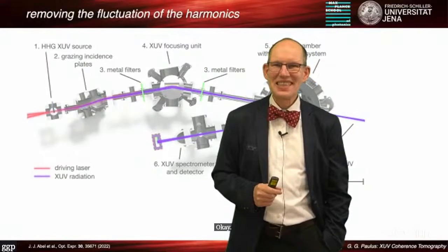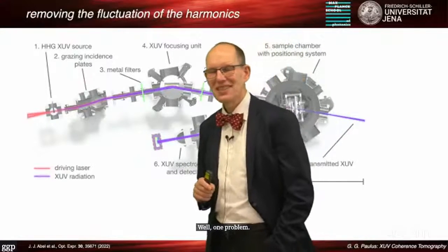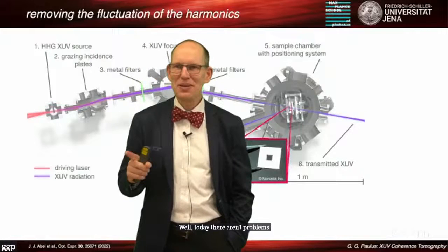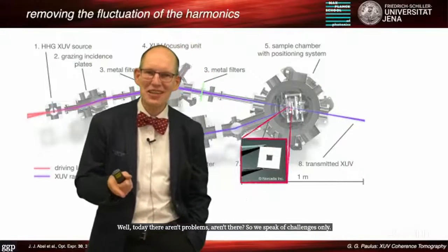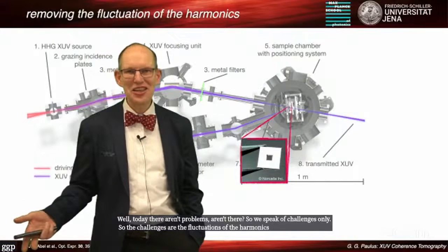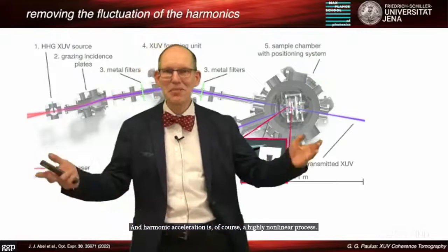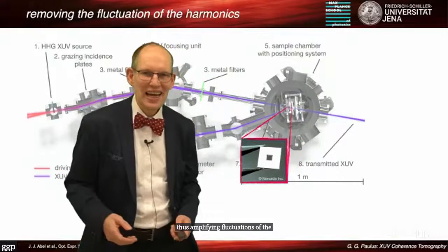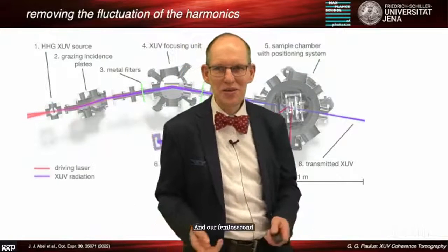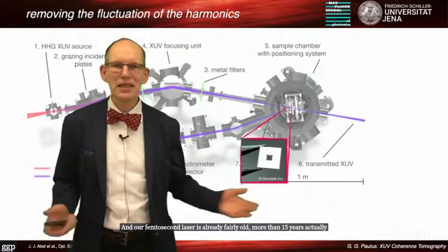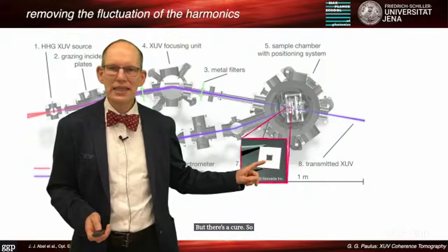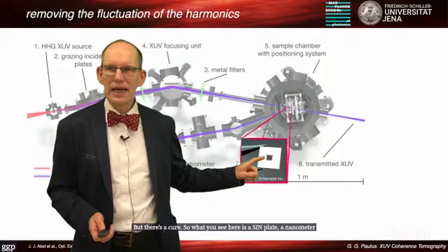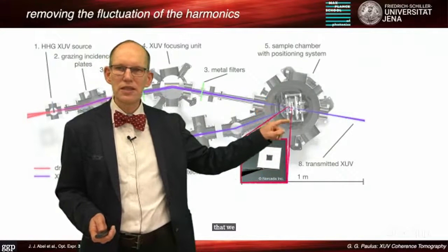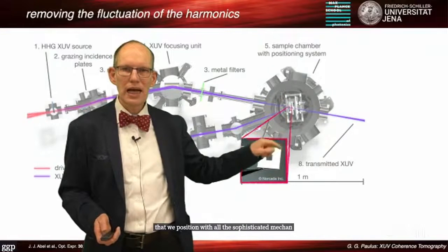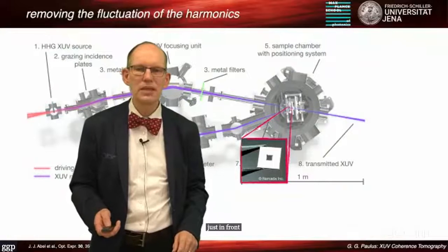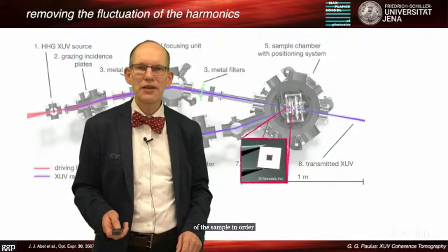Okay, well, one problem. Today there aren't problems, are there? So we speak of challenges only. The challenges are the fluctuations of the harmonics. High harmonic generation is, of course, a highly nonlinear process, thus amplifying fluctuations of the driving laser. And our femtosecond laser is already fairly old, more than 15 years actually, but there's a cure. What you see here is a thin plate, a nanometer thin plate, that we position with all the sophisticated nanomechanics just in front of the sample in order to get a live reference.